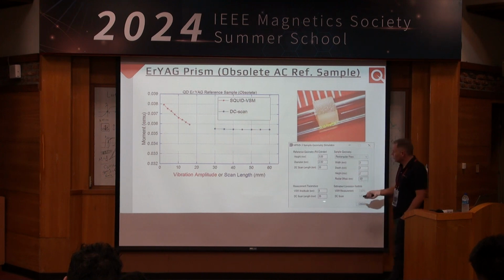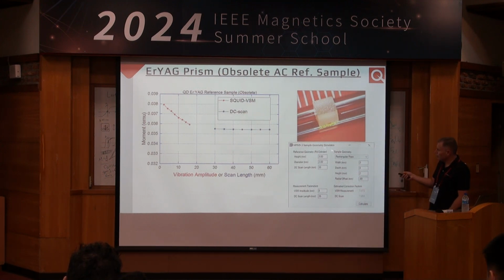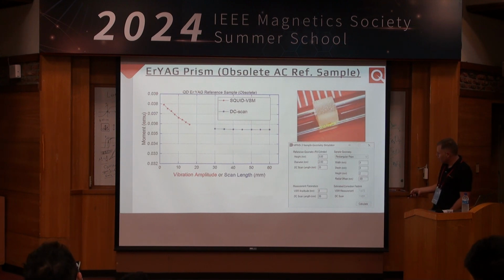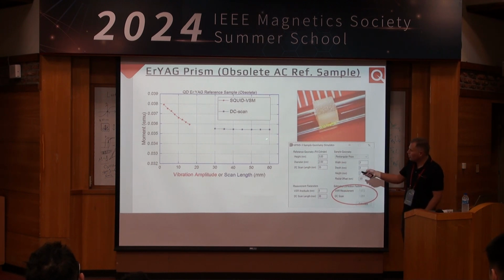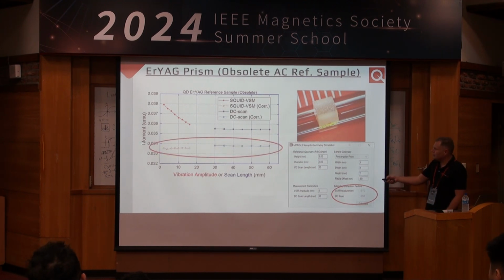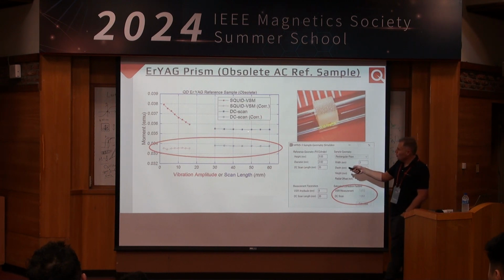Well, we provide a little tool for the user where you can put in your material parameters, rectangular prism, the size of this, etc., and we will spit out a correction factor for you. So if we put in these correction factors and we correct our data, we can actually turn it into data that looks like this. So again, we've shifted this down. These are now within 1% of each other, and this is a flat line.